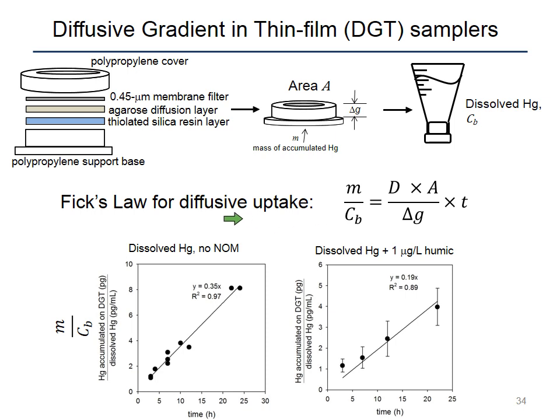And what I have on the bottom here are graphs where we've taken these samplers and exposed them to aqueous solutions of dissolved mercury. And we show that it does seem to follow this Fick's law equation. So we have the amount of mercury accumulated on the resin divided by what's dissolved in solution. And you can see that this uptake is linear with time, where the slope is proportional to the diffusion coefficient.